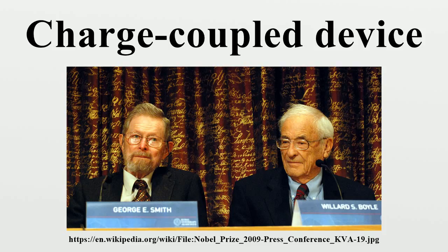Simon M. Sze details the advantages of a buried channel device. This thin layer is fully depleted and the accumulated photogenerated charge is kept away from the surface. This structure has the advantages of higher transfer efficiency and lower dark current, from reduced surface recombination. The penalty is smaller charge capacity, by a factor of 2 to 3 compared to the surface channel CCD.